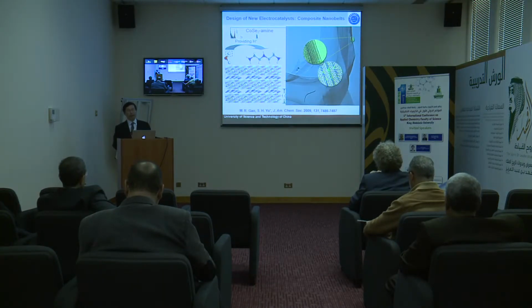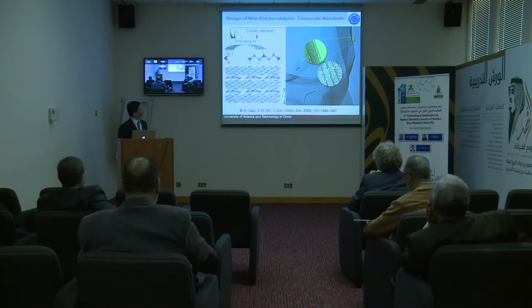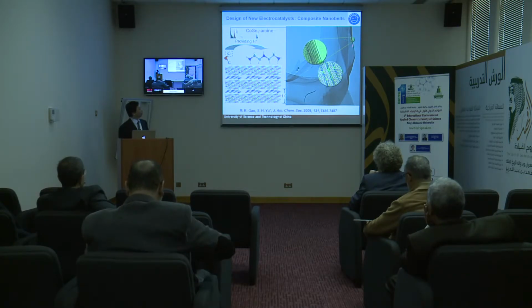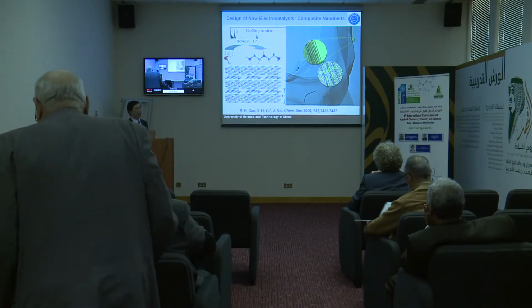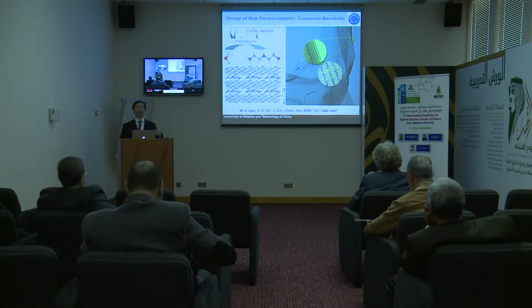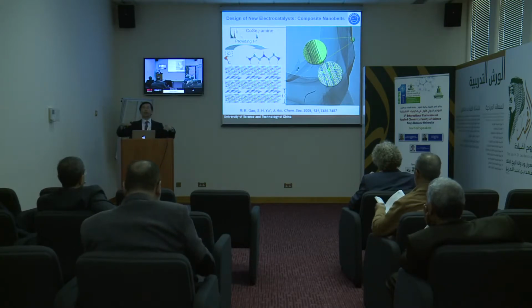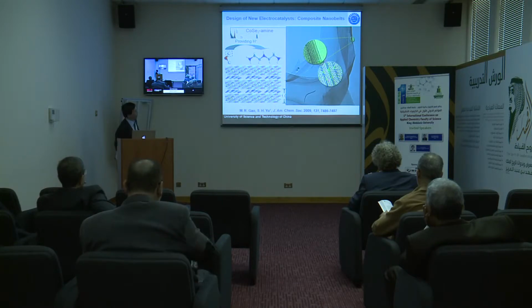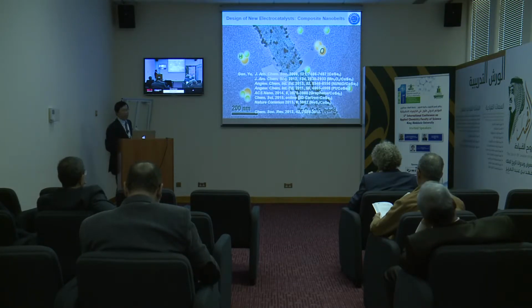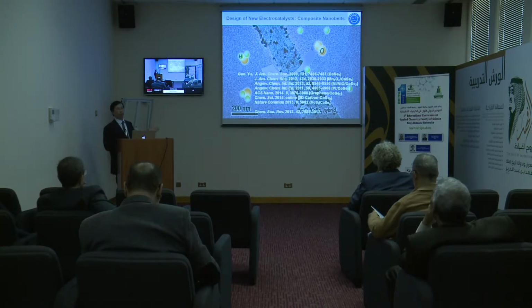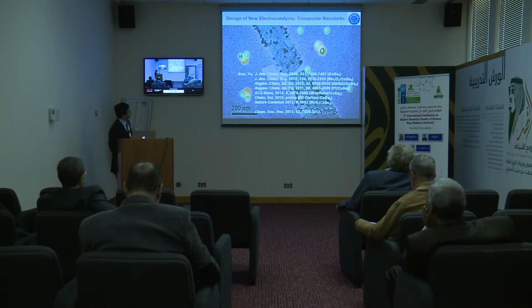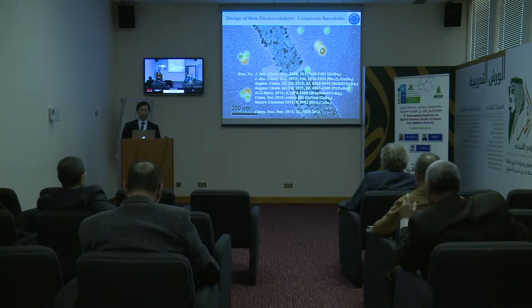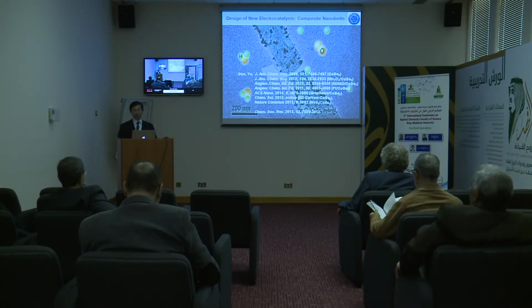For one-dimensional nanowires or nanoribbons, there is another strategy to modify the surface. This is a nanoribbon called cobalt selenide, which we discovered in 2009. You can see it is a very ultra-thin nanowire. If you look at the nanoribbon in the thickness direction, you can identify well-defined few layers. These are cobalt selenide slabs, isolated and separated by a monolayer of amine molecules in this very new system. Then we use them as a matrix. You can marry this nanoribbon with different materials, bringing new material onto the surface of the nanoribbon, so that you can get many kinds of nanocomposite materials, which show promise for accessing new electrocatalysis systems in the future.